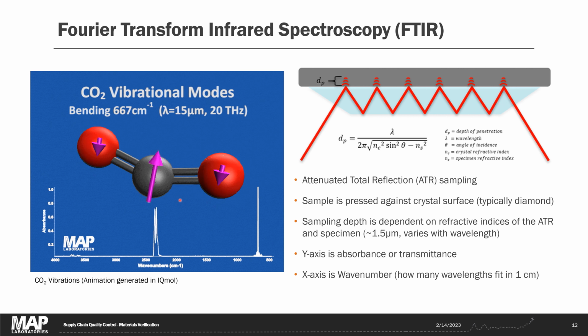Here I've run FTIR spectroscopy on the new vendor material and on the old vendor material, and we can see that there are some definite differences between the two. First off, we ran a library search and we found that BHT, a common antioxidant, butylated hydroxytoluene, was the best match. Library searches are a great place to start, but they can be misleading and they can false positive on things, so it's helpful to understand a little bit more about the spectrum.